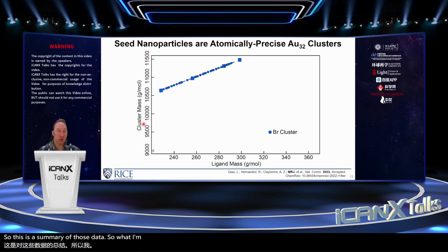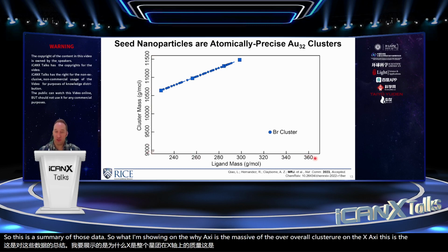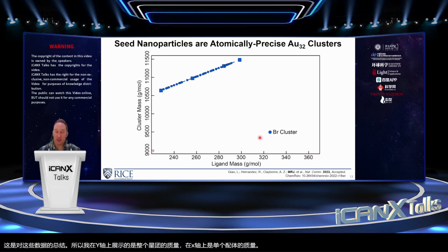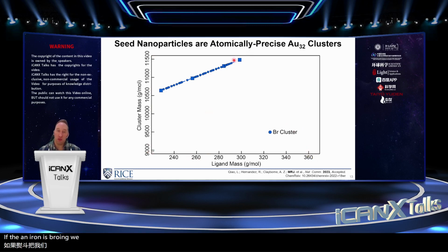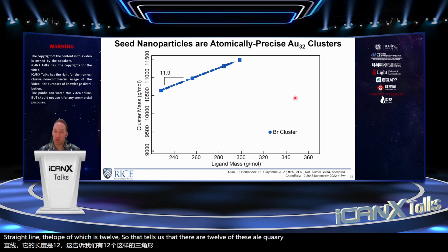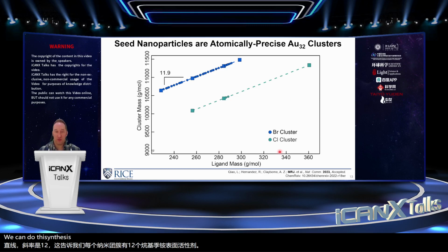What I'm showing on the y-axis is the mass of the overall cluster. On the x-axis is the mass of the individual ligand. If the anion is bromine, we get all of these points that lie along this beautiful straight line, the slope of which is 12. So that tells us that there are 12 of these alkyl quaternary ammonium surfactants per nanocluster. We can do the synthesis all over again, but just use surfactants where chlorine is our anion. We see exactly the same line with the same slope of 12, showing us there are 12 ligands.